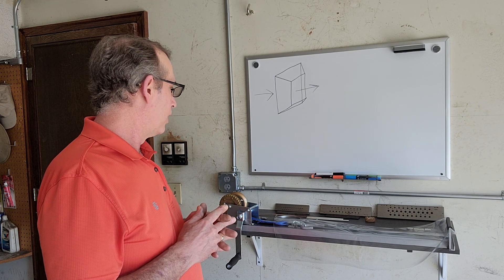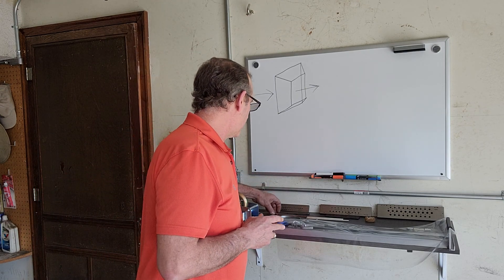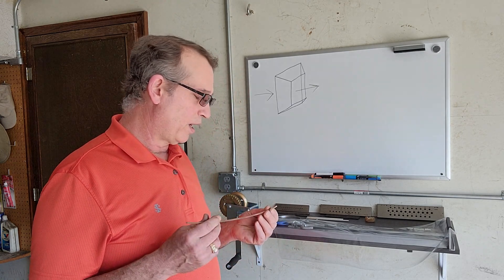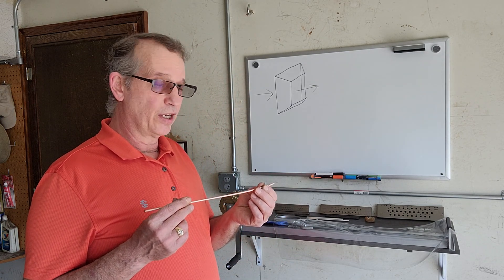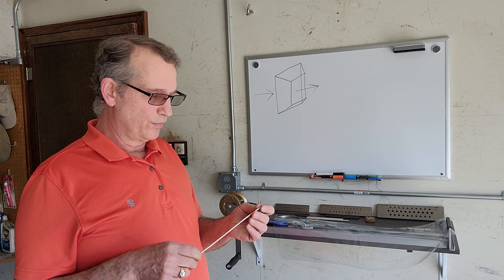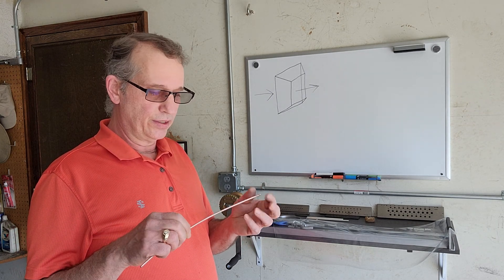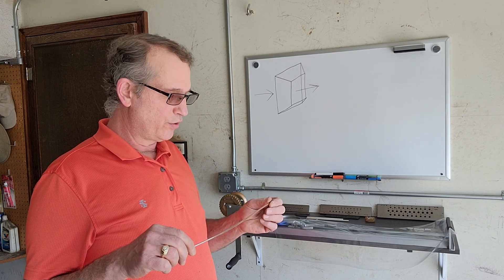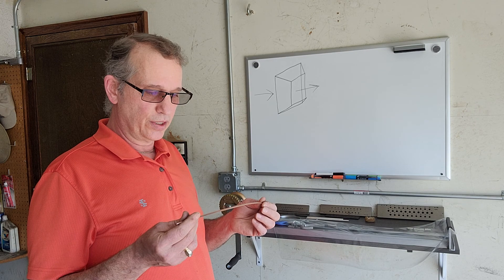Now let's talk a little bit about the wire and how you need to prepare it when you're getting ready to draw. The first thing you do is make sure that the wire is clean, dead soft, or somewhere near dead soft. From dead soft you can actually draw down through three steps and get quite a bit of change in profile and change in length.